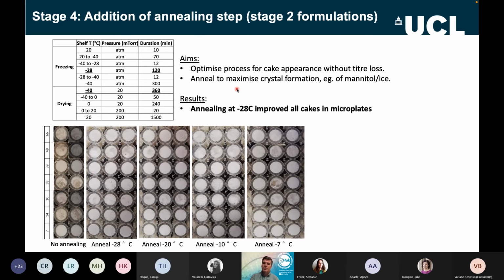So the trade-off was a bit of a conundrum, as I said. So one thing we thought about was, what can we do to improve the cake in other ways that might not lose the titer? A classic way to do that is to put into the process what's called an annealing step. We're using mannitol, for example, in our formulations, and that's known to not properly crystallize if you quickly freeze it, so you get into a glassy state. One thing you can do is take the temperature back up briefly. It's still cold, like -28, -30, but originally freezing at -40 or -50. You take it up a little bit, and that allows some more crystals to form. So it gets you a more crystalline state, which hopefully would improve your cake morphology, make it look nicer and not all melting.